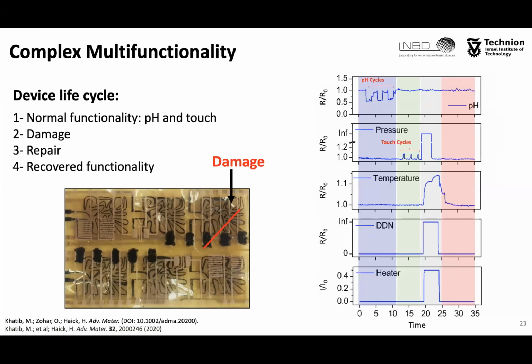As you can see on the right side of the slide, cutting through the temperature and pH sensors by a blade down to the DDN layer, the damage detecting network layer, led to the activation of the heater, which in turn increased the local temperature and led to complete healing of the device.